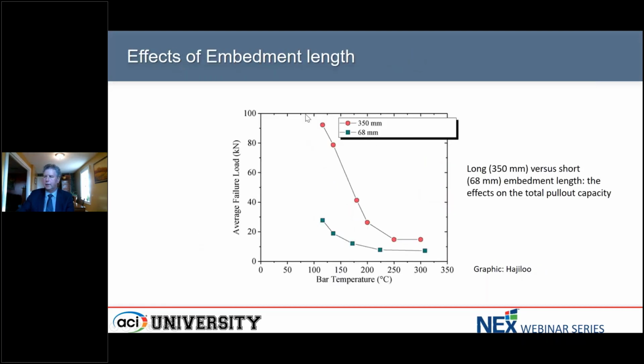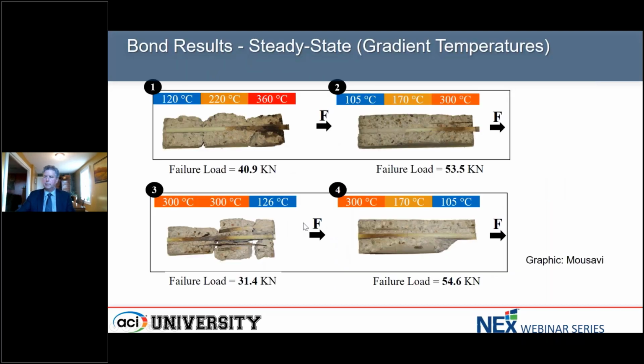But this does the comparison of when we have a longer length versus a shorter length. And it does show that as long as the bar temperatures can be kept in this range of 100 to 200 degrees centigrade, so we're talking about maybe 200 to 400 degrees Fahrenheit in this case, that we are getting quite a bit of benefit of additional length. As temperatures get hotter over the length, then that benefit falls off, and providing extra length doesn't make much of a difference.